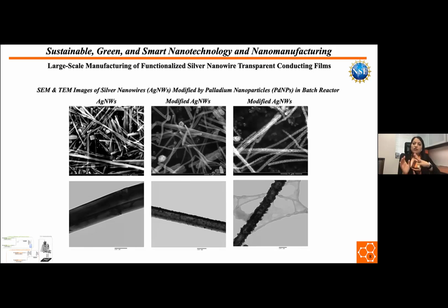And these reactions have been done in a kind of batch system, which means that we produce silver nanowires in the millifluidic reactor, we separate them, wash them, and then we have them as a suspension to which we add the palladium precursor or other reagent to modify their surface using palladium nanoparticles. And this is the reason that we call that batch modification.